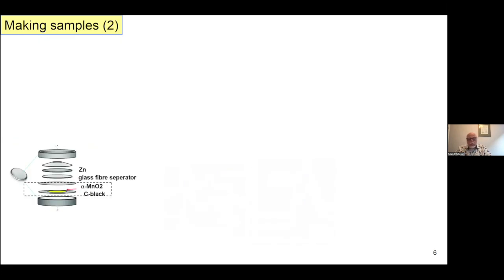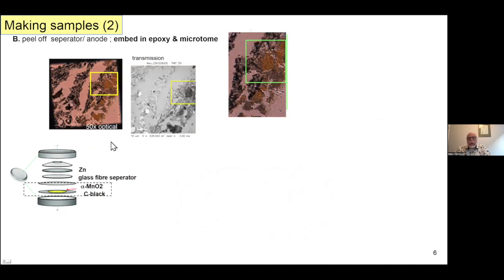And so here we wanted to focus on the cathode material, the manganese dioxide. And what we did then was we peeled off the upper part of this structure, the glass fiber separator and the anode, but left the rest of it, the carbon black and the manganese dioxide intact, and then embedded that in an epoxy and microtomed it. So again, this is that material. It's the same slide as a couple ago.